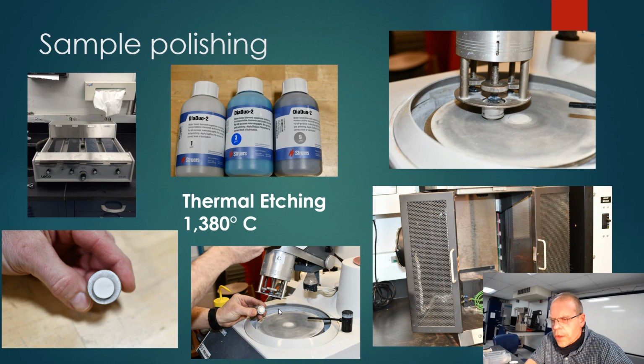Okay? And so one of the final steps we have to do, if you remember back to 41, before you got images of your 4140 steel, we had to etch, and we ended up using a substance called nital, a mixture of methyl alcohol and nitric acid. For the ceramic pieces, we found out that we can actually do this just by heating. We're not going to heat way back up to the temperatures we had, but we're going to thermal etch. We're going to go to about 1380 degrees C for just 30 minutes, and believe it or not, this is going to bring out some of the images that we want to see.